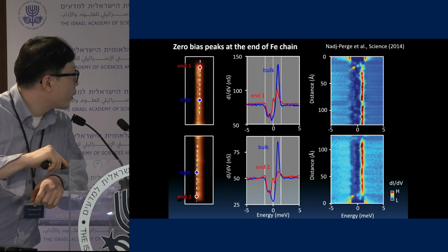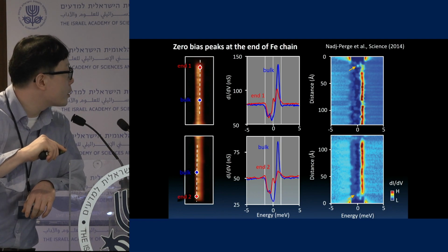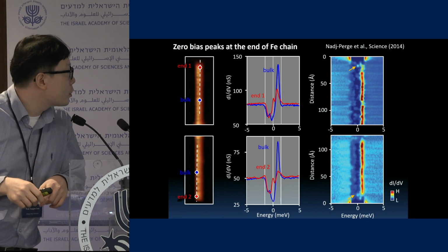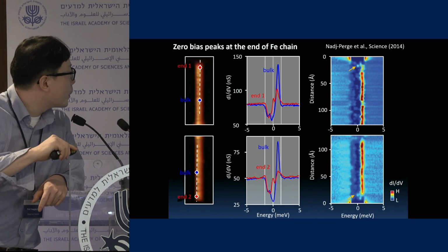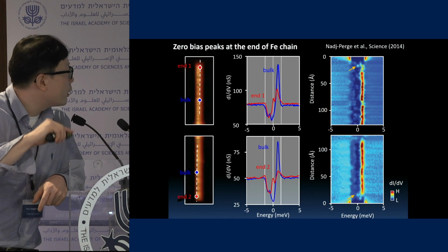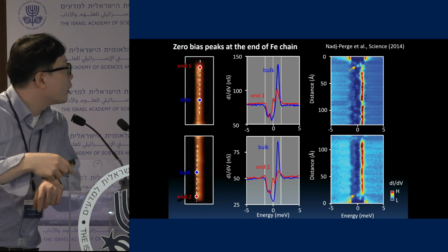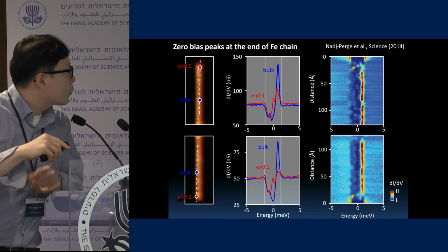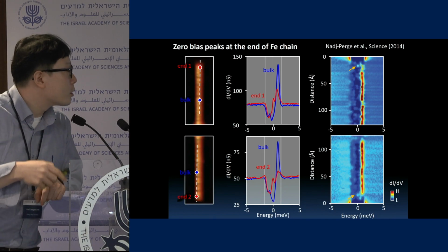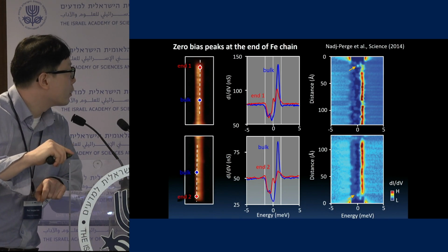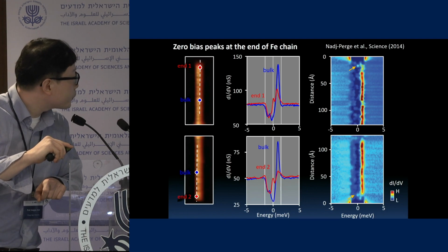This is the topograph. As I mentioned, the scanning tunneling microscope tells you the structure of the system. This is the one-atom-wide chain made of iron, and this is the upper part and the lower part. Actually, in between there are some unknown structures. It's hard to understand, but at least there are two clean parts, elongated, with a length scale of about 5 nanometers to 20 nanometers or so. So these are relatively long nanowires.